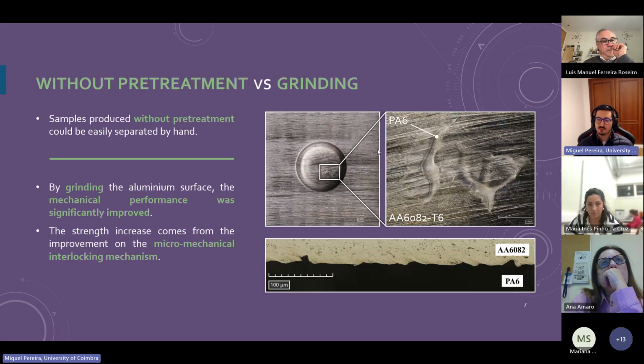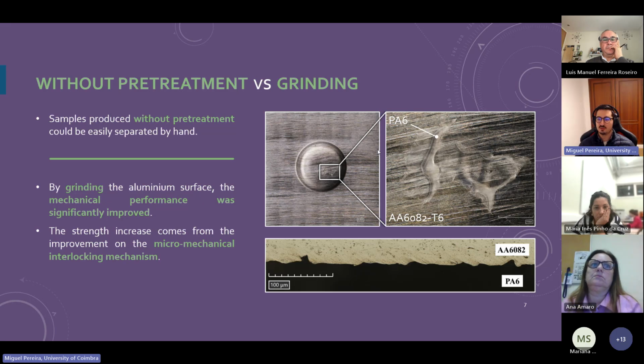So first, as mentioned, we tested the production of joints without pretreating the aluminum, and we observed that these joints were easily separated by hand, which indicated the weakness of the joints produced in this condition. So we tested another approach, which was grinding the aluminum surface with sandpaper, and this resulted in an improvement of mechanical performance. The improvement of mechanical performance was attributed to the creation of a micro-interlocking mechanism, which is basically when we have the cooling or the solidification of the polymeric material in the rugosities created by the grinding procedure.